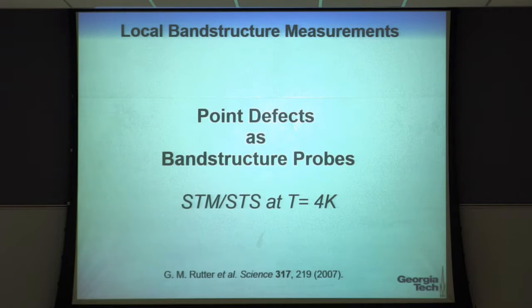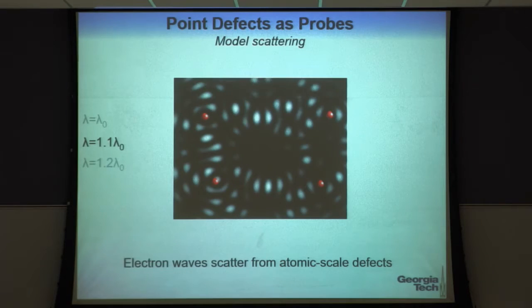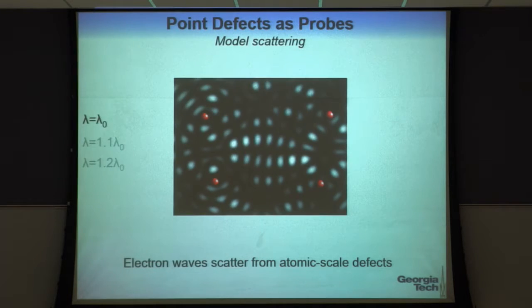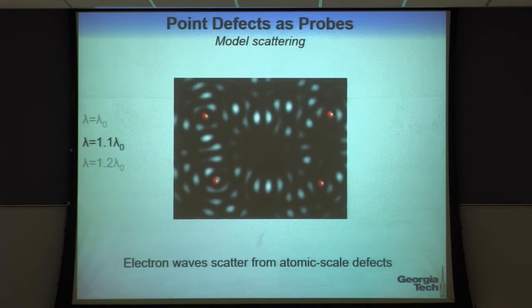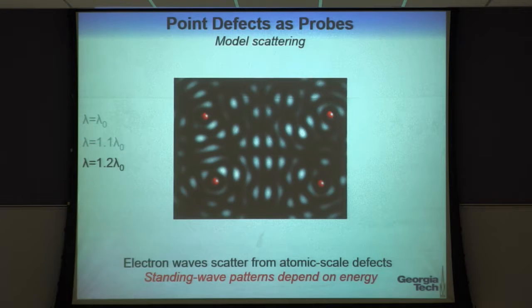So the first method that one can use is to use point defects that might occur in a material as themselves band structure probes, okay? And the way you do that is, well, first make a little model. These are point defects in a material, and let me just pretend I have waves in 2 dimensions that are scattering from them, and then I get a nodal structure due to interference of those waves. And if I change the wavelength of the waves, the nodal structure changes. Change the wavelength again, the nodal structure changes. And of course, changing the wavelength is changing the electron energy.